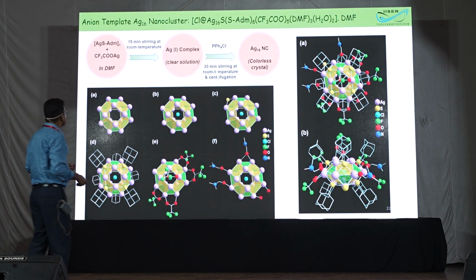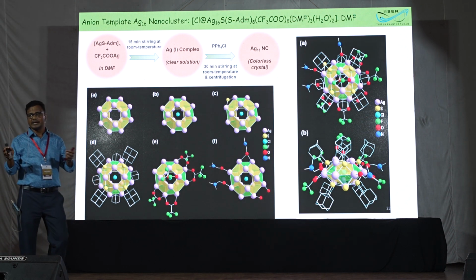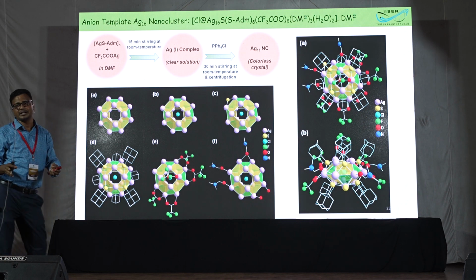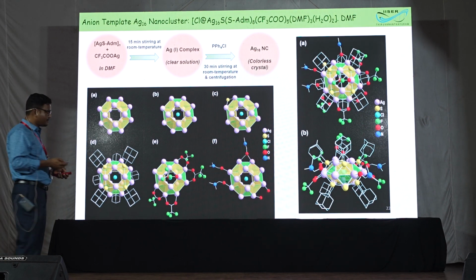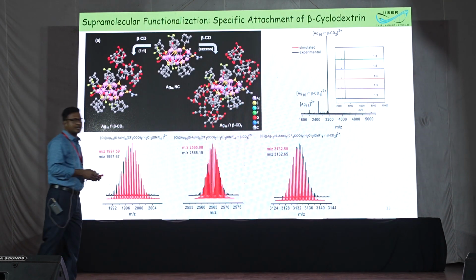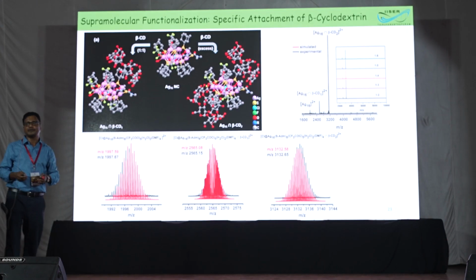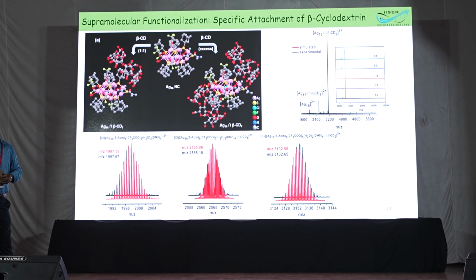So when we thought that adamantane thiol is bulky, it can suppress the non-radiative pathway and could give some emission at room temperature, but unfortunately this cluster is not emissive. So we protect the adamantane thiol with a cap of beta-CD and make a composite. Though we have 8 adamantane thiols, only 2 can be protected because of the steric bulkiness, and the composite was characterized by mass spectrometry.